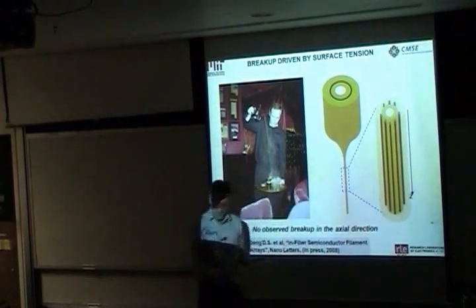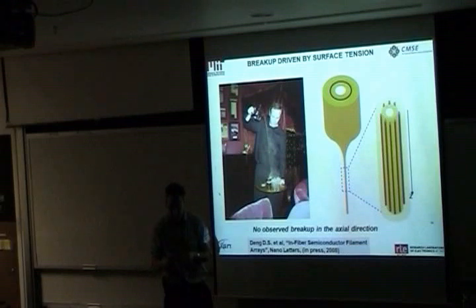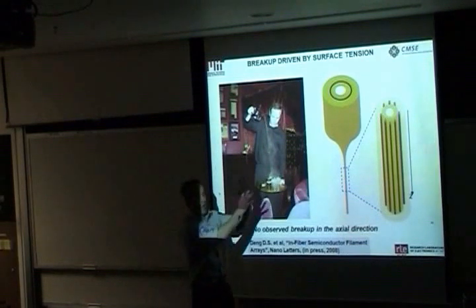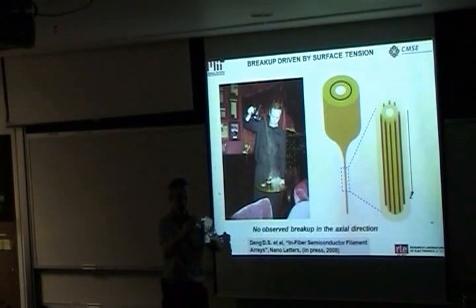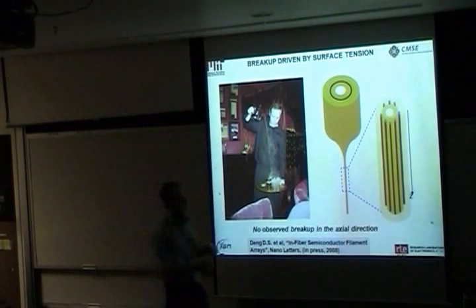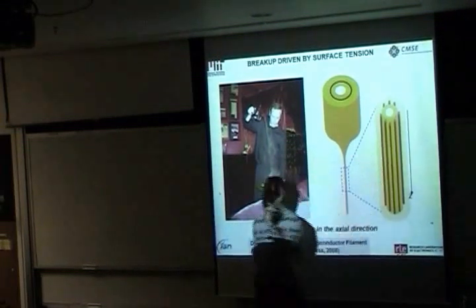And then you draw this into a fiber, and you say, perfect. Here's my layer of metal, and I should just have a fiber with a nice little sheet of metal inside. And in fact, as we launched into this project, we just took a picture of the preform and said, this is a done deal. Well, it turns out that when you examine the preform, it does not have a layer in it at all, but it has these very fine cylinders going through it.